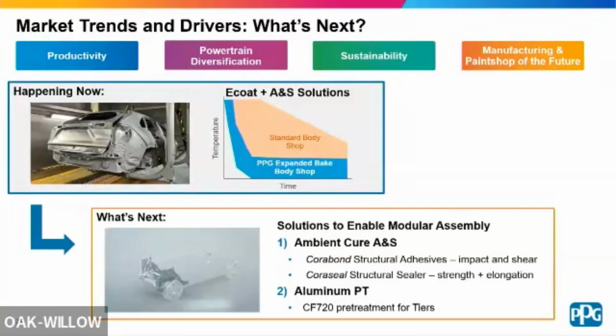During the curing or paint bake process, the aluminum substrate also experiences change to meet a mechanical target. So it's an essential step for the aluminum structure. This is part of the consideration when you are lowering the curing temperature. For aluminum, going from 180 degrees C down to 140 degrees C is a huge change in the mechanical property. So we are interested in how to get OEMs to adopt this technology.